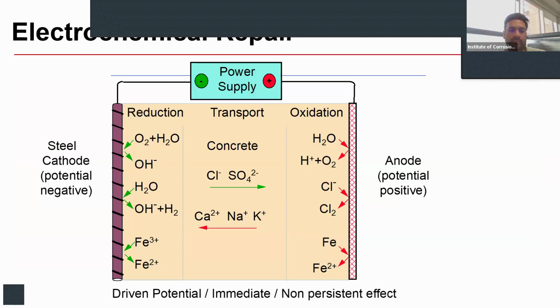Three things are majorly happening. Firstly, chloride, which was around the steel bar causing corrosion, is repelled, so chloride starts to move away from the steel bar. Secondly, hydroxide ions start to form on the steel surface, causing the film which had broken down to start repassivating again. Thirdly, the potential of the anodic site starts to depress.